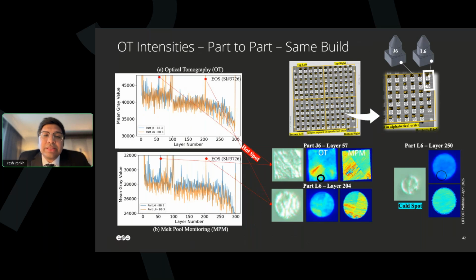That tells me this is very important, because now I'm locating the J6 and L6 spots on the right hand side, and just wanted to see what J6 and L6 for baseline build 3 look like, and why they're not exactly the same. What does the initial spike on the high gray value side mean? My logic tells me that if it's a high gray value, it's a hot spot. Because of the small particle size, it might fly here and there, as you saw in that video. It's a finicky process. There's a lot going on. So it's very hard to pinpoint these variations. But we tried getting a few.